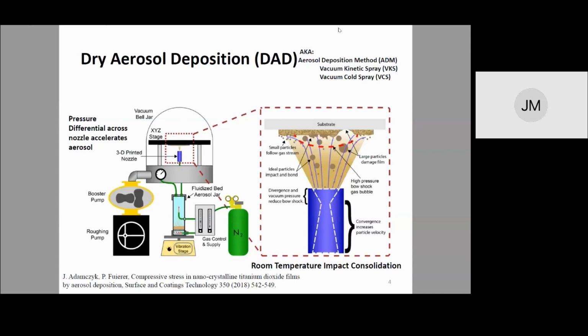On the left is a rough illustration of our setup here at New Mexico Tech. We have a roughing and a booster pump that reduces our vacuum pressure in our chamber to around 2 torr. So these films are sprayed in a rough vacuum. We use a vibration stage as well as a nitrogen gas supply to create a fluidized bed of our powder to aid in the aerosolization.